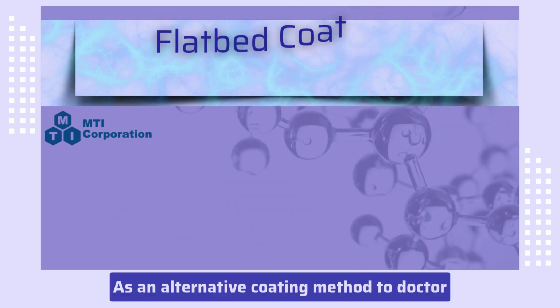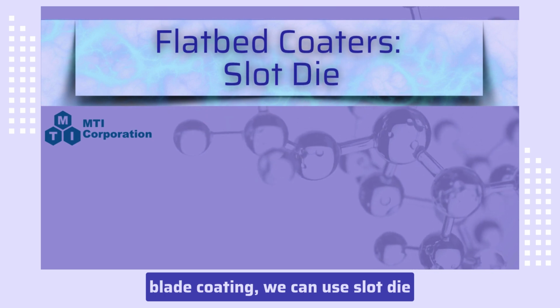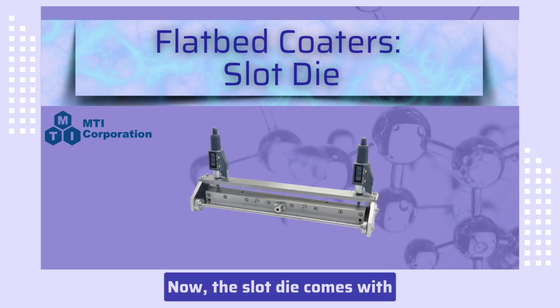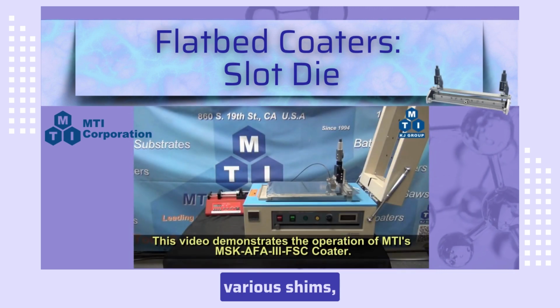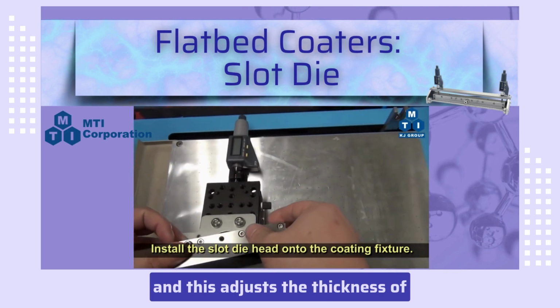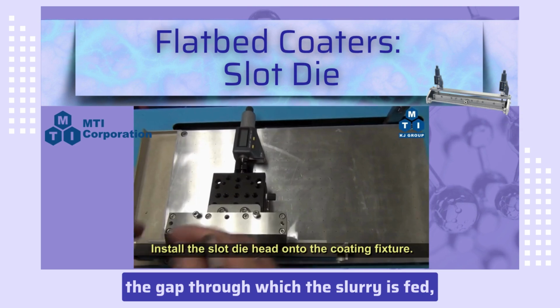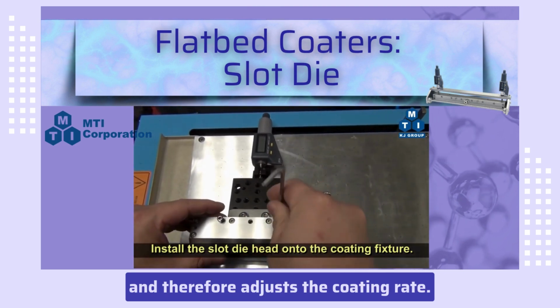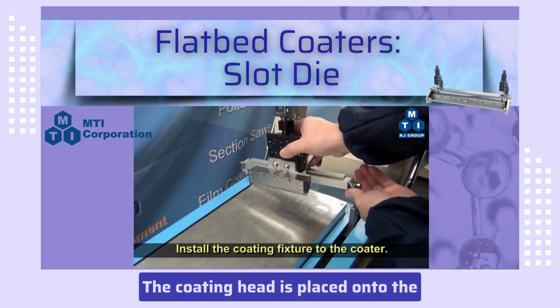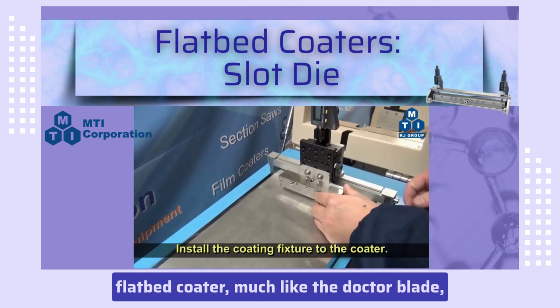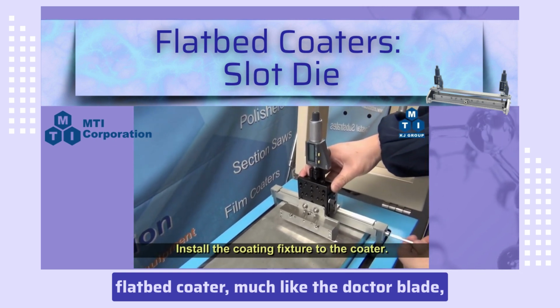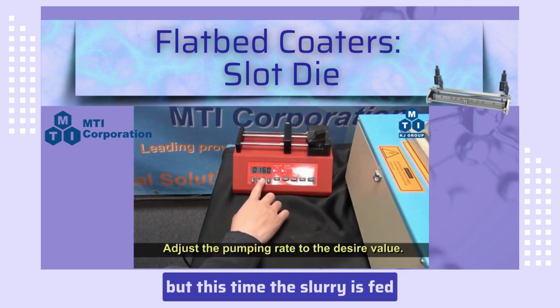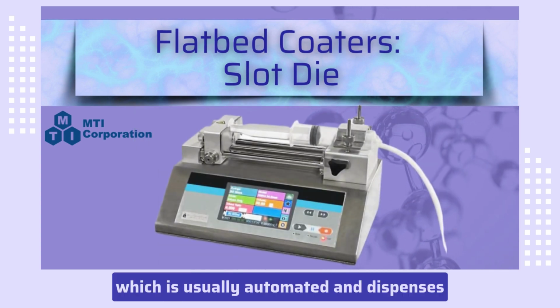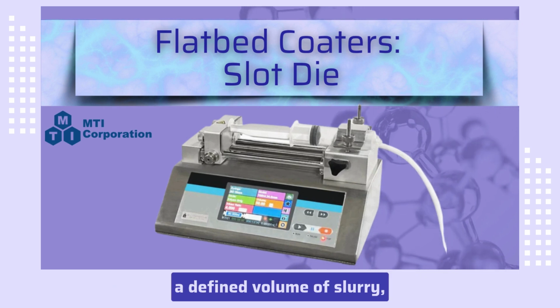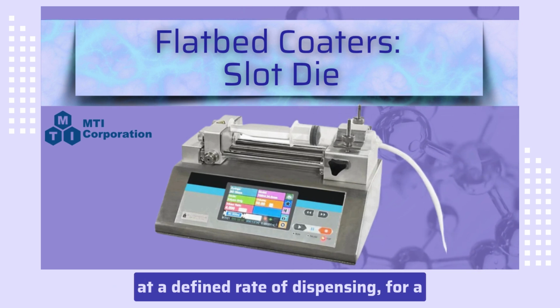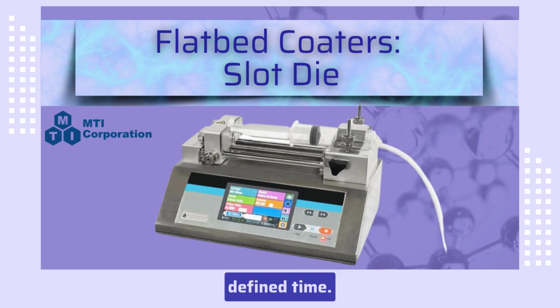As an alternative coating method to doctor blade coating, we can use slot die coating. Now the slot die comes with various shims, and this adjusts the thickness of the gap through which the slurry is fed and therefore adjusts the coating rate. The coating head is placed onto the flatbed coater much like the doctor blade, but this time the slurry is fed using a syringe pump, which is usually automated and dispenses a defined volume of slurry at a defined rate of dispensing for a defined time.